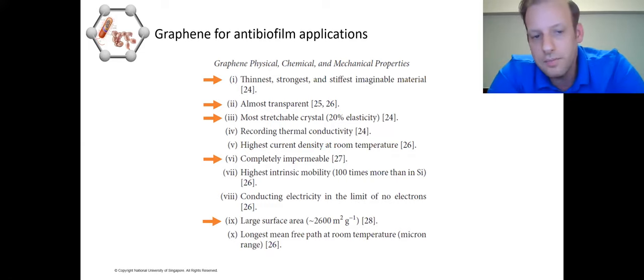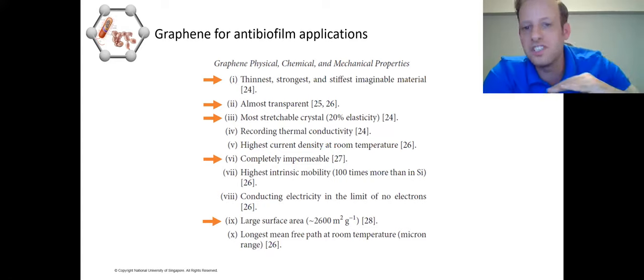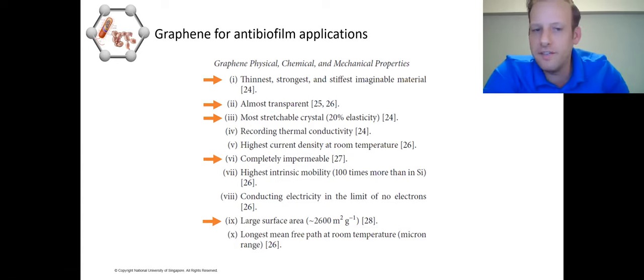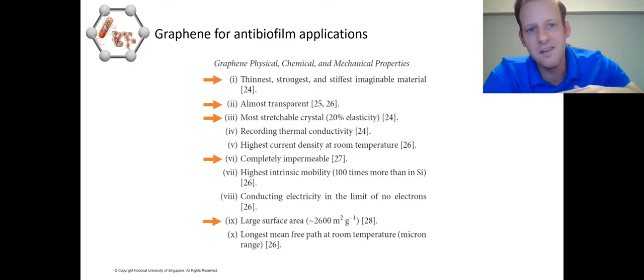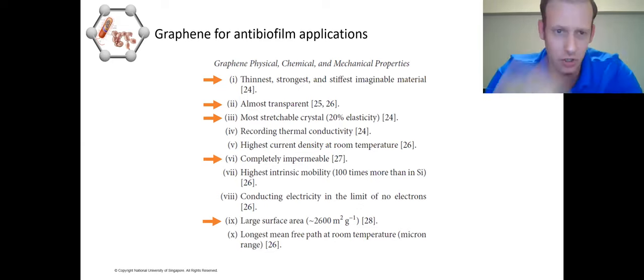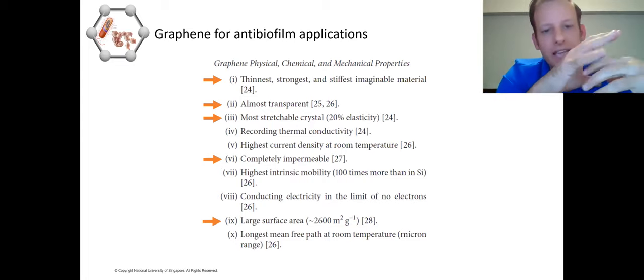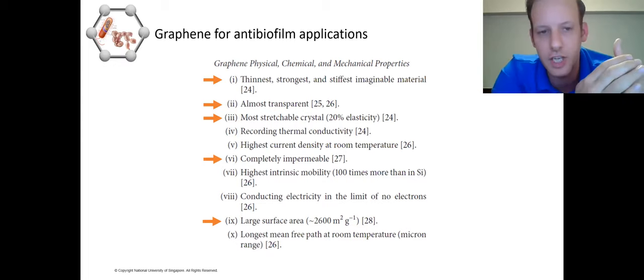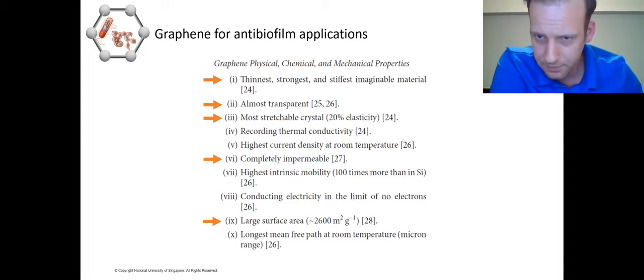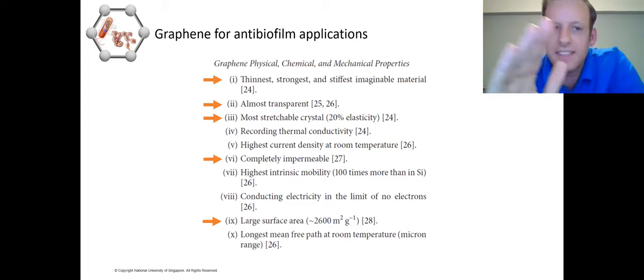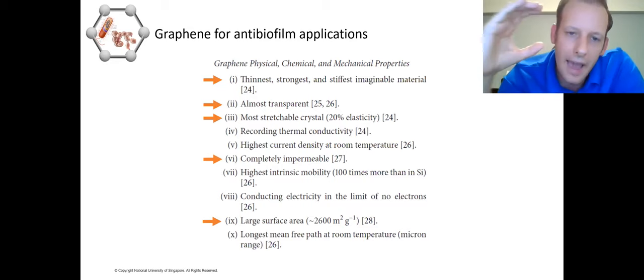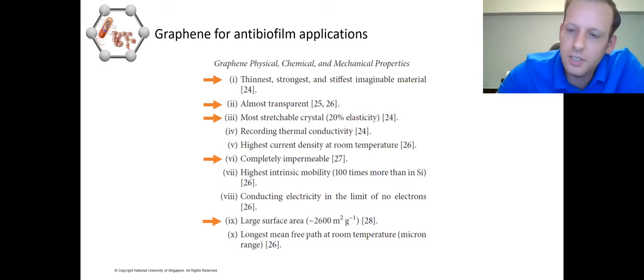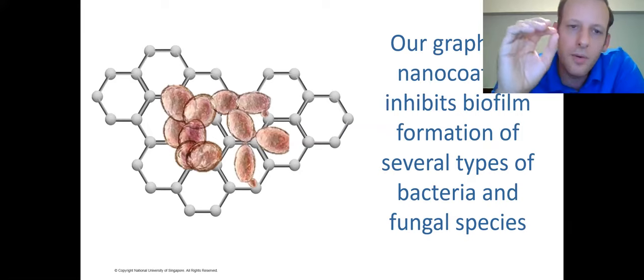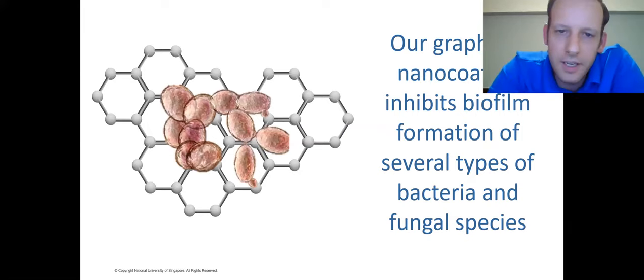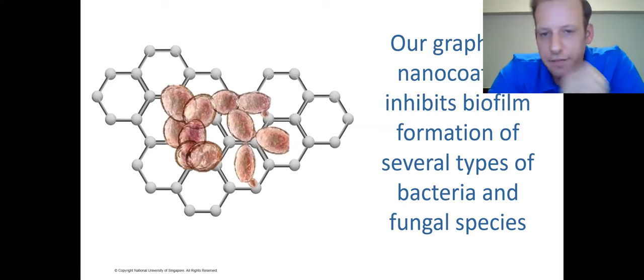Because it's stretchable and has a very large surface area, I can coat several types of objects. And during the last 4 to 5 years, we have been very successful in coating not only flat surfaces, but nearly every sort of 3D shape that has appeared to us. So graphene is able in a way to adapt to the surface of materials, regardless of their shape, as long as you use the right technology to do that. In the next slides, I'm gonna show you the summary of everything we have observed in the past years that allows us to say very categorically that our graphene nanocoating inhibits biofilm formation from several types of bacteria and fungal species.